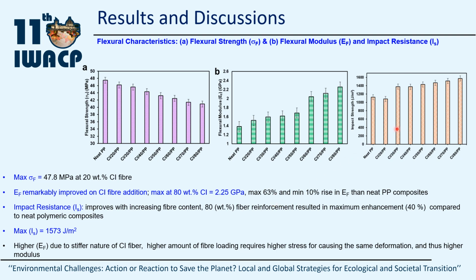In terms of impact resistance, which basically describes the capacity of the developed composite to resist shock loads, it was also found to be improved with increasing fiber content, and the maximum enhancement was found to be 40% as compared to the neat polypropylene composites. The maximum value attained was 1573 joule per meter square.